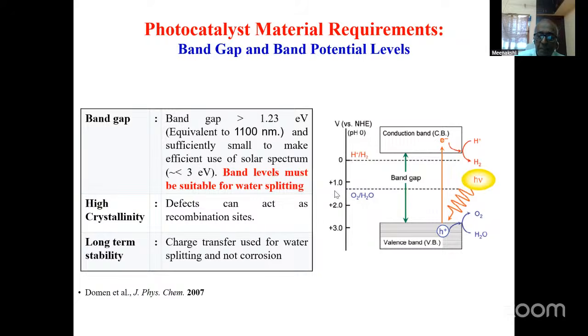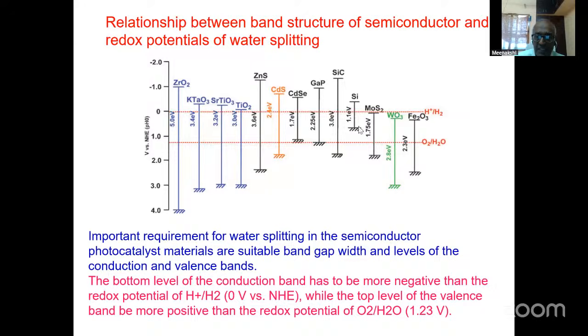Here you can see the band potentials of several semiconductor oxides: zirconium oxide, potassium tantalate, strontium titanate, titanium dioxide, and so on. All those with conduction band levels above zero are able to produce hydrogen, that is, split the water into hydrogen, because they are more negative. When the level is below zero, it is positive, and they cannot reduce the H plus ion to hydrogen. So all these catalysts having levels above zero are capable of producing hydrogen from the water.